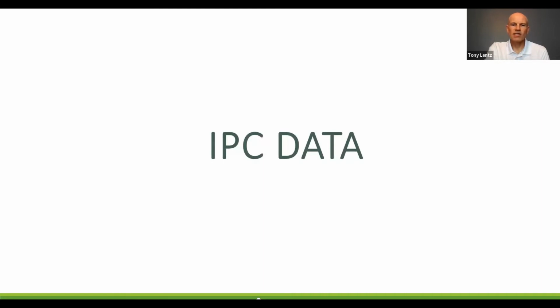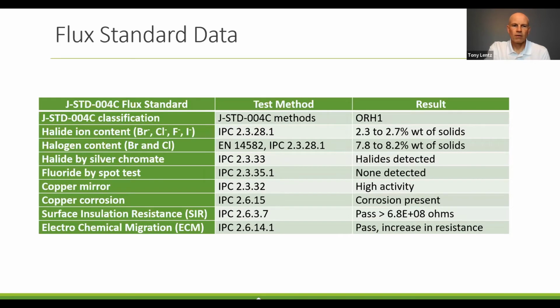Here's the IPC testing data to go along with this solder paste. So here's the J-STD-004C flux classification. It's classified as an ORH1, so it is high activity and does contain halides. It also contains halogen activators. So it's a highly active solder paste. And it definitely helps to improve wetting, especially on difficult surfaces. But in this case, special materials were chosen in order to improve voiding potential.